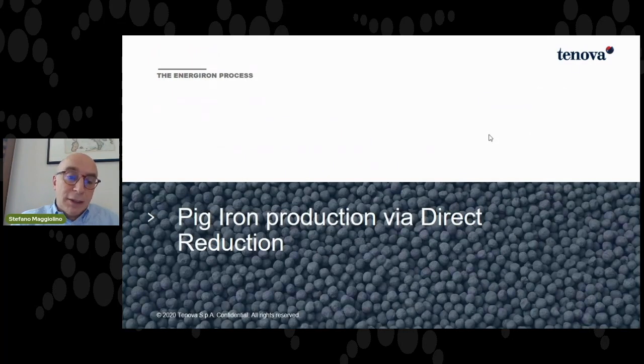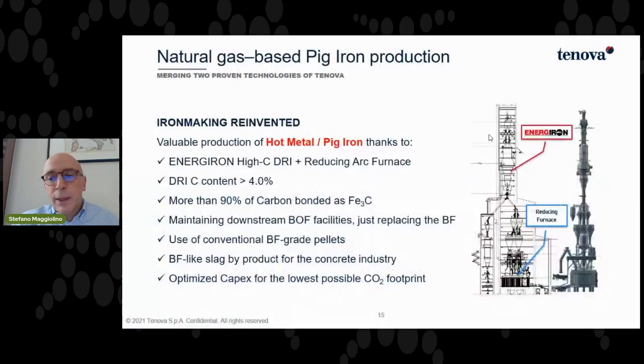But the novelty that we're proposing in the market is pig iron production through direct reduction. The concept is easy. Being capable of producing high carbon DRI up to 4.5% carbon, we just need to split the hot DRI from the metal and the gangue. And we can do that in a reducing furnace, what we call an open slag bath furnace, which is a technology supplied by Tenova.